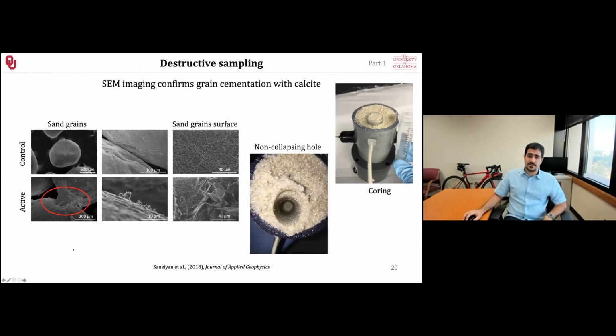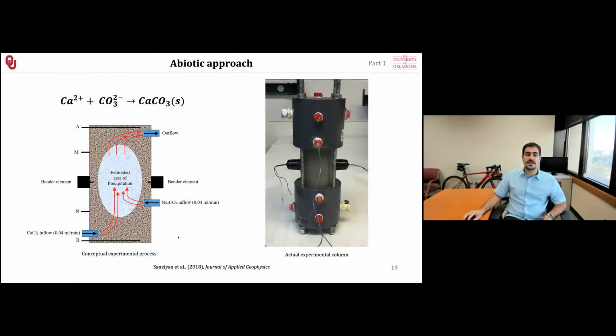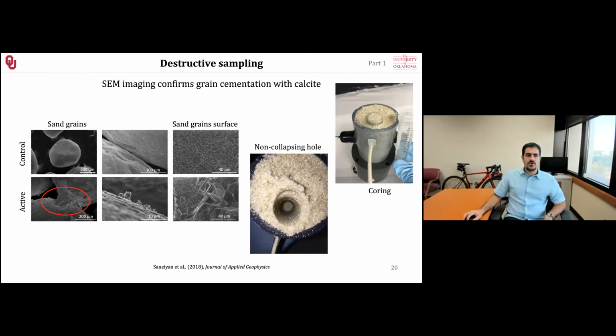We basically destructed the sample, took the soil and put it under the SEM microscope, and we were able to see that the control sample, which did not have the carbonate solution in it and only the calcium-rich solution, showed no evidence of precipitation in between the grains or on the surface of the grains. But the one that had the carbonate, we see the cementation in between soil grains, as well as the evidence of precipitation on the surface of the quartz grains. You can clearly see the rhombohedral calcite crystals in here under the microscope.